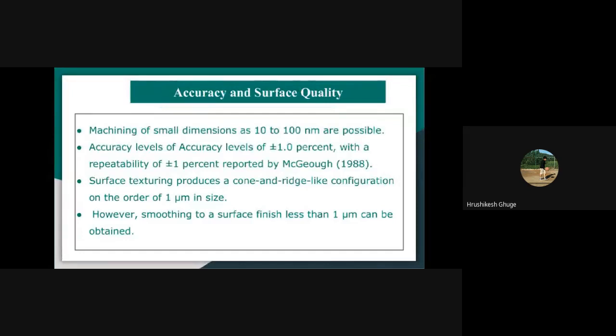Then let us discuss the accuracy and surface quality. Small dimensions such as 10 to 100 nanometers are possible using ion beam machining. The slope of the side walls of the machined surface and its surface finish are determined by the angle of incidence of your ion beam. An accuracy level of plus minus 1 percent, with a repeatability of plus minus 1 percent, has been reported by the researcher. The name of the researcher I have written here. The surface structuring produced is cone and ridge like configuration on the order of 1 micron in size. Smoothing to a surface finish of less than 1 micron can be obtained using this process.